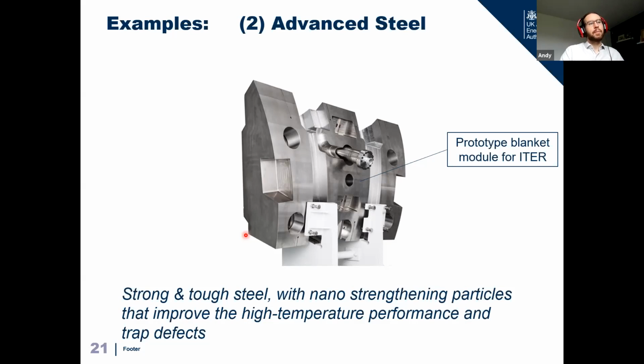So our estimate is that if you have just what we call a ferritic steel, so that's without nickel, and we irradiate that in a fusion reactor, after 100 years we would be able to recycle that fairly easily. So iron on its own is a really good element for use in a fusion reactor, and it's not giving us that really long-lived radioactive waste that you get from a fission reactor, for example.